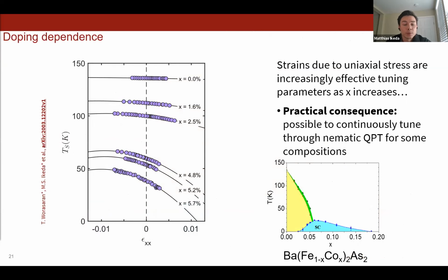Such evidence can be found by studying this property across the phase diagram of cobalt doped barium iron arsenide. And so the figure on the left-hand side here shows the nematic phase transition temperature as a response to strain for various compositions across the phase diagram. At first sight, it's already clear that as we increase the cobalt concentration going towards the optimally doped regions in the phase diagram, strain becomes more and more a sensitive tuning parameter for the nematic transition. And that is true for the linear response of the transition temperature, as well as for the nonlinear response.